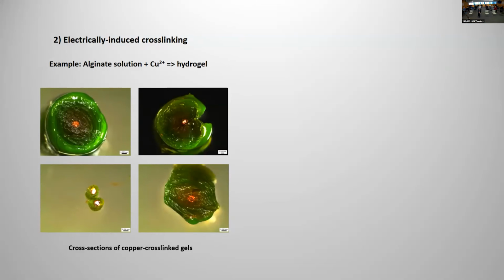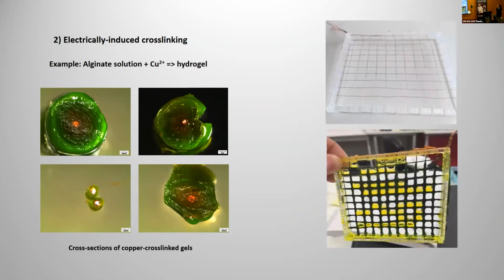So by passing a current through the copper fiber, so the copper wire, you spit out Cu2+ ions, which will cross-link the alginate bath that it's sitting in and slowly grow this gel around it. And it's really interesting because the closer you get to that copper wire, the harder the gel, and you get this complex system. Not really sure what you want to use it for, but we showed that you could make really complex grids of this stuff just by threading copper wire through, having a single anode, and then I was using a base cathode of aluminium foil, and it was growing these fantastic gels in a grid structure.